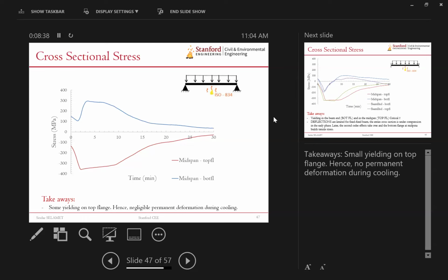And then you get more axial stress, pretty much in tension in the bottom flange, and then more in the top flange when the axial load is increasing here. But later on, there is a funneling behavior, basically because of the yielding reduction. You get less and less stresses developing in the beam, where towards the end, as you would expect, the moment gets close to 0. So the difference between those two gets close to 0.